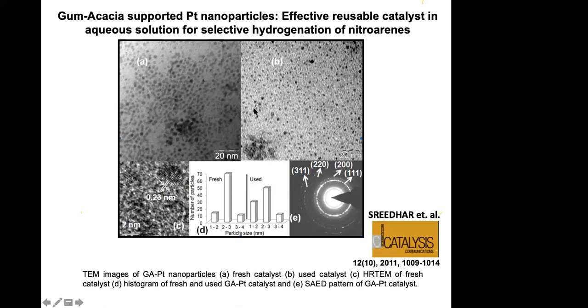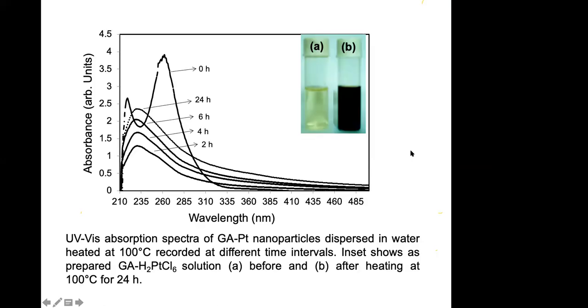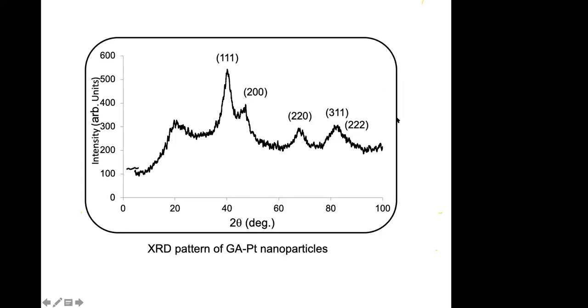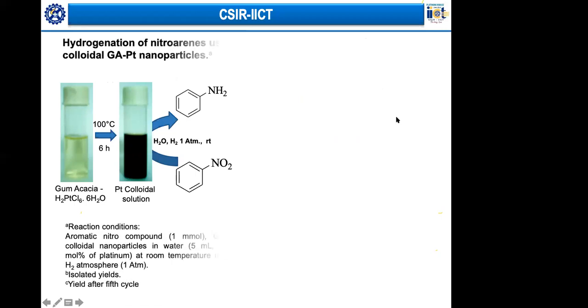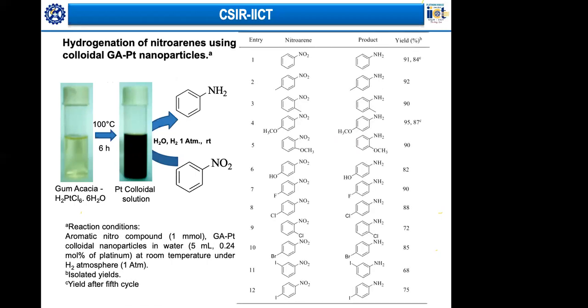So this is before reaction and this is after reaction. Even after reaction, the size is almost the same, about 2 to 3 nanometers. Then this is how we monitored at different stages, at 0 hours and at about 6 hours, you see a change in color, and that is how we differentiate, along with XRD. And we used this for this kind of reaction. Here we used water as a solvent, again hydrogen as a balloon, and at room temperature we were able to do hydrogenation of nitroarenes to amines.